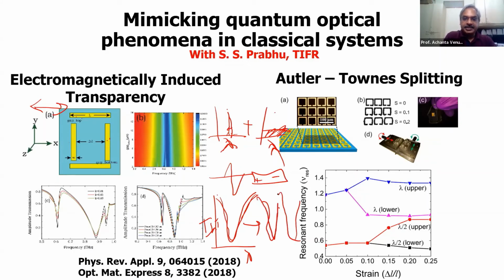So within this spectral dip, now you are seeing, sorry, I'm not sure how. Okay, so basically here you will see an enhancement in transmission. So this is the so-called electromagnetically induced transparency, which is known again in atomic systems. So this is the dipolar dip, and then this enhancement in transmission that we are seeing is because of this coupling with the quadrupolar resonance.